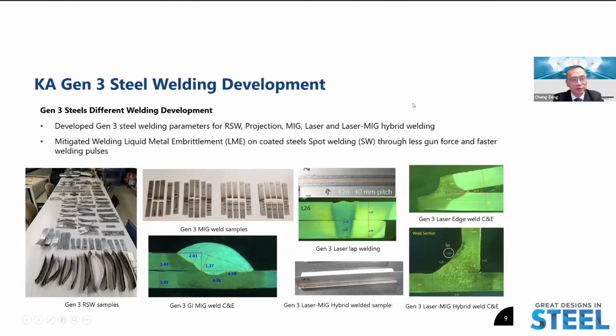Okay, so you can see here, these are the spot welding samples. We welded over 300 samples in order to get different geometry tips, different materials, and different combinations. And then we did the analysis on the pull tensile test, cross tension test. You will see that in the next slide. Then, among others, we did MIG welding samples. And then we did laser welding samples.